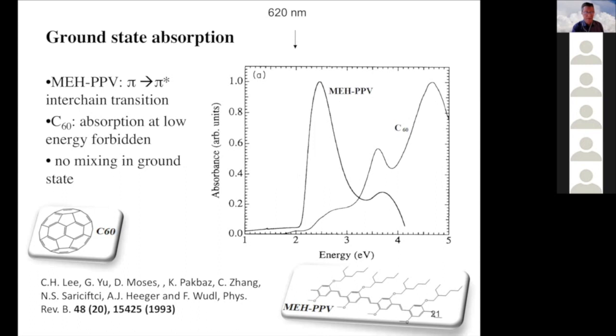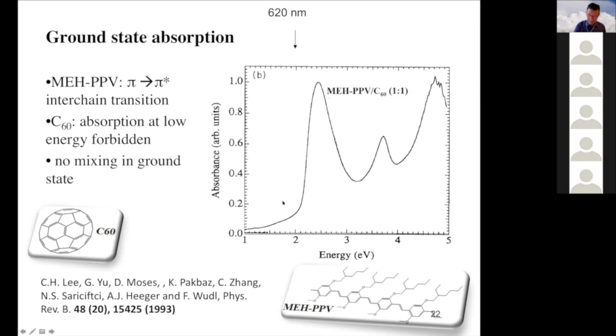If we look at the UV absorption spectrum, then we see the separate components here. You actually see that in the visible area, this paper comes from a physics group, so they put the wavelength in electron volts, but this is the low energy side. So C60 does not absorb a lot of light in the visible because it's so symmetric. The symmetry makes the transition forbidden. If we look at the mixture, then you see that it's almost the same, only in the low energy region there's a small change, but this indicates that in the ground state, these molecules do not interact a lot. There's no strong interaction in the ground state.